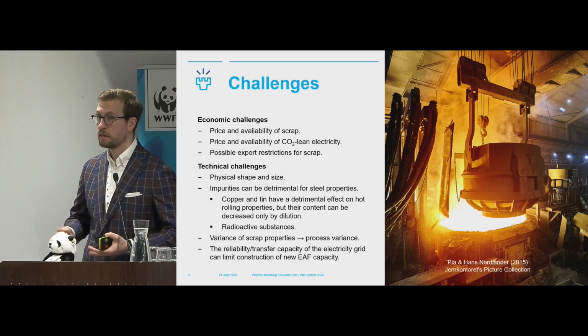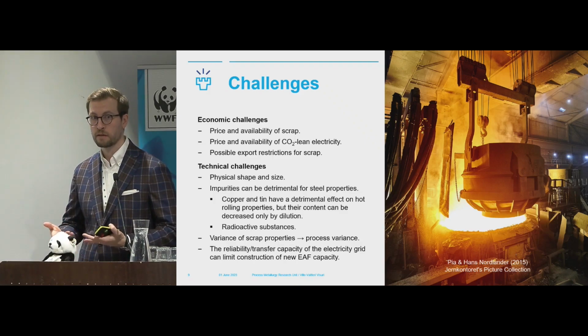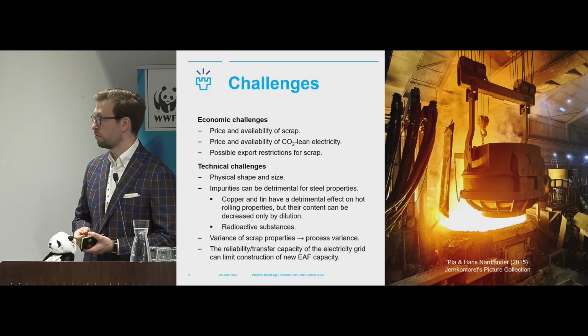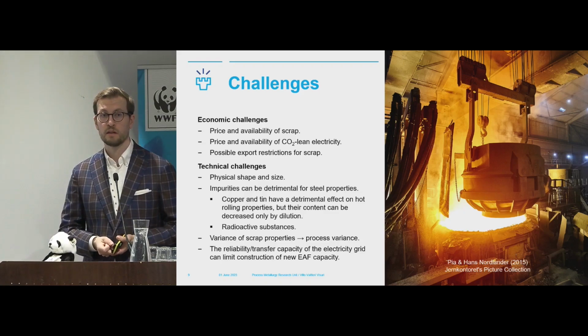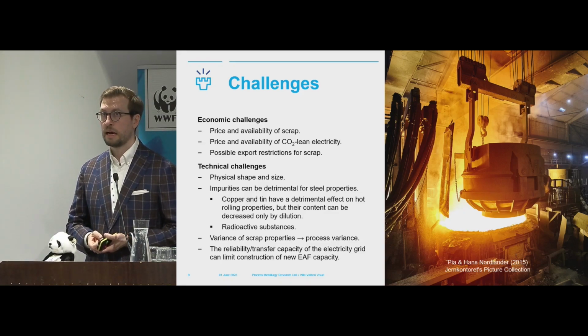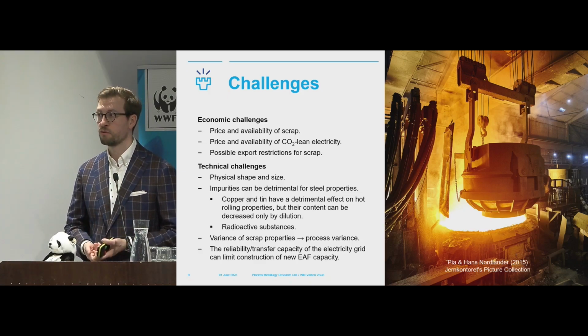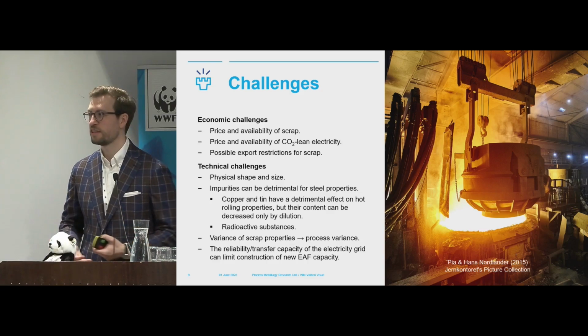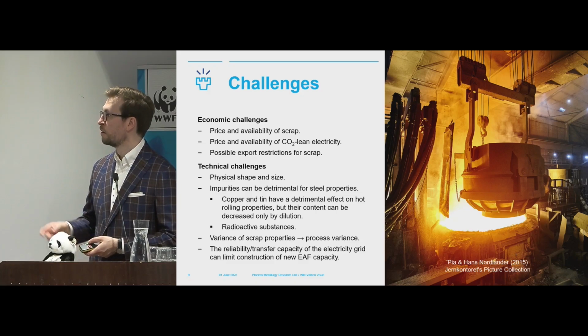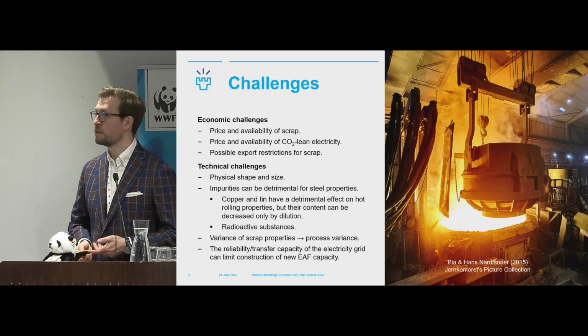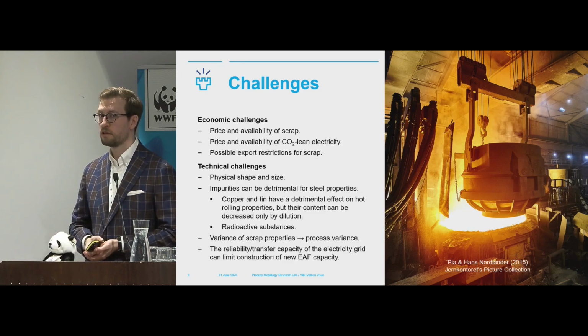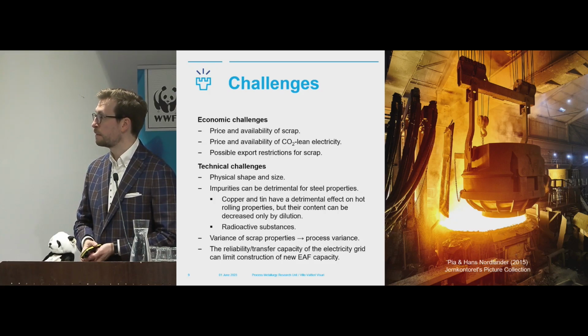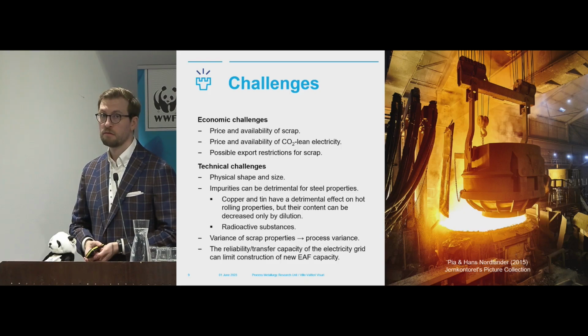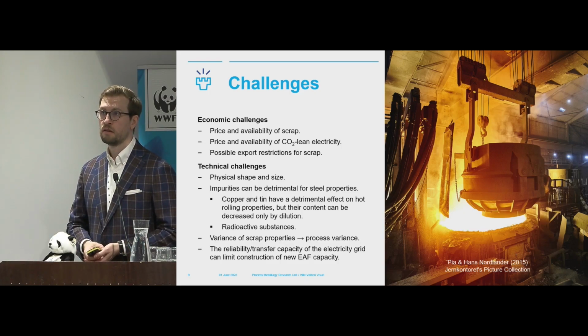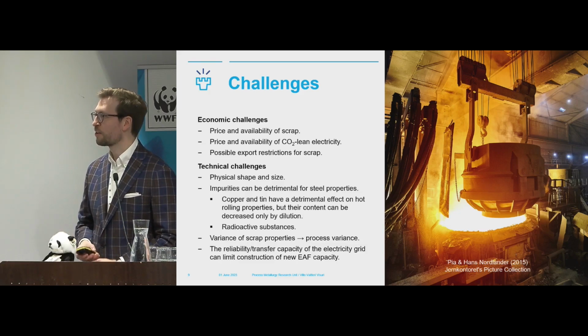Then for the technical challenges that limit the use, of course, what kind of scrap we have in physical shape. If it's very small, it might be difficult to handle. If it's very large, you need to dismantle it. Then impurities are also something that are very detrimental for steel properties, and in this electric arc furnace route, we don't have that good possibilities to remove them as in the integrated route, which is more or less designed around removing impurities like phosphorus and carbon and sulfur. There are some specific elements which are quite a nuisance, especially copper, but for instance in stainless steel making cobalt is also a nuisance. And okay, some of these can be removed, but species like copper can more or less only be diluted, so we cannot get rid of it, but we can just dilute it.